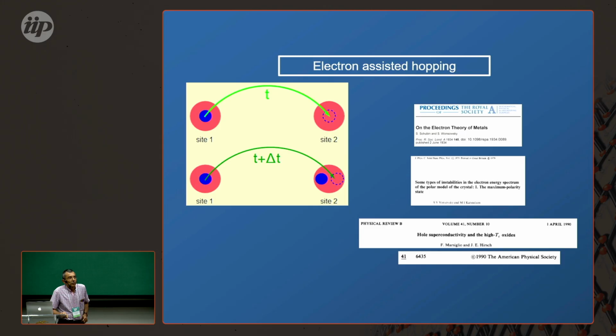If you try to project the interactions onto a local basis for the flat bands, you need to take into account not only density-density interactions, but also that when you put an electron in a Wannier function, which has very funny Fidget spinner shapes with a long, strong trigonal distortion, you induce changes in the on-site potential in nearby Wannier functions.